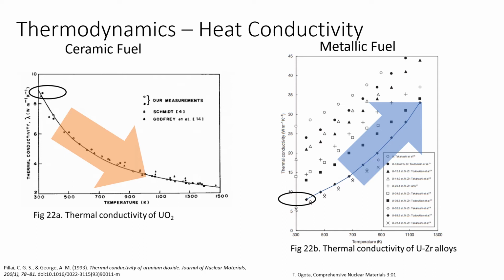This has a couple implications. Ceramic fuel will have a much higher centerline temperature and greater temperature gradients that induce more residual stress and strain, whereas metallic fuels will become better conductors when they become hotter, which is more desirable in an accident condition. Furthermore, it allows us to run our fuel with greater safety margins due to a lower centerline temperature.